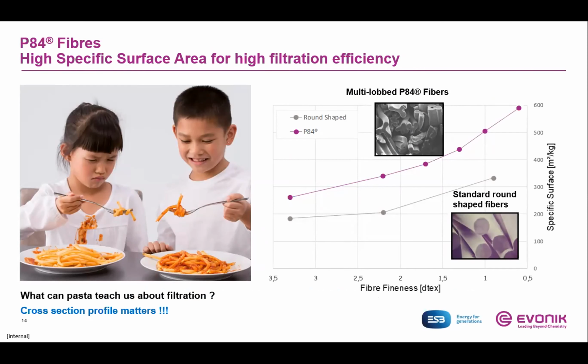The most crucial thing when it comes to filtration is that you need to provide a high specific surface area. This can be done in two ways: either you generate very fine fibers, or you use irregularly shaped fibers. This is the unique thing about the P84. It is the only really multi-lobe shaped fiber available on the market, and it offers something like 60–70% more specific surface area compared to a standard round-shaped fiber of the same thickness.